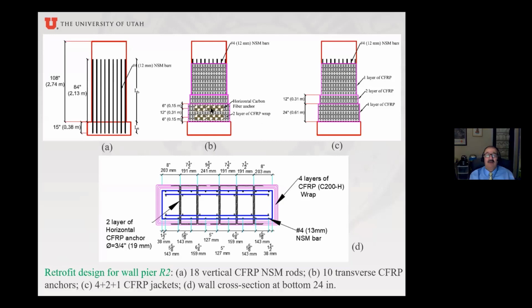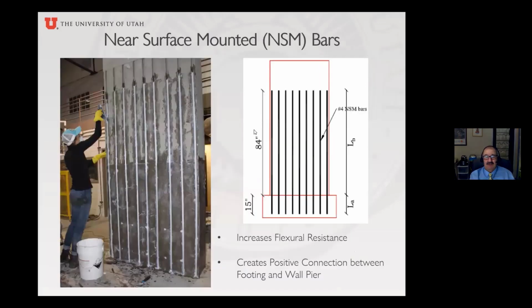Other than that, we had a similar situation, 10 horizontal carbon fiber anchors, 3/4 inches. We didn't have any vertical sheets because these carbon fiber bars are very good in tension. And we had only the hoop layers, 4, 2, and 1, like I showed you before. So in this case, instead of 10 carbon fiber anchors, we had 18 vertical rods. And everything else is pretty much the same.